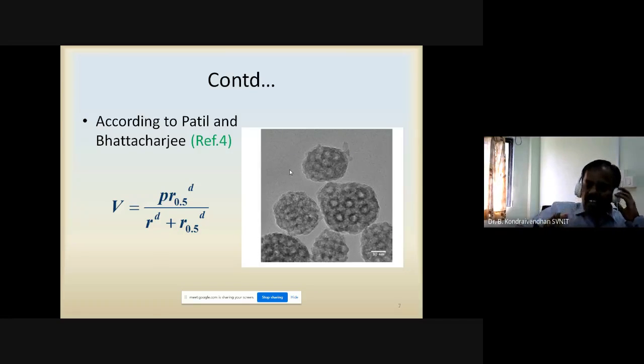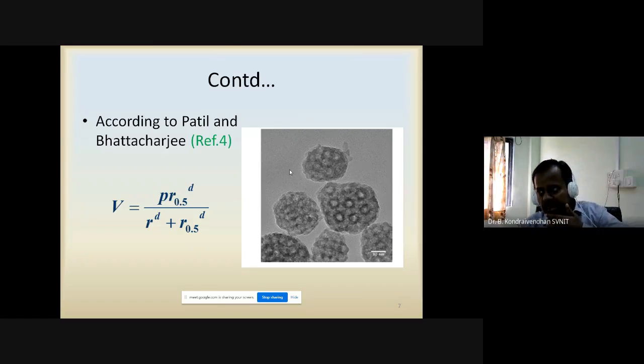There is a lot of research that has been done on this. Actually, we are the pioneers in this research also. Professor Bhattacharya and Patil have done some work on this cement-based material, and they found that pore size distribution is governed by three parameters. One is the permeable porosity P, R.5 is the mean distribution radius, and D is the dispersion coefficient. So I am clearly explaining here what R.5 is: R.5 is the pore entry radius, D is the dispersion coefficient, that is the distance between the pores, and P is the permeable porosity. If you know these three parameters, and you are able to model them as functions of simple mix parameters like water-cement ratio, curing age, and mean cement particle diameter, then it is possible to determine the pore size distribution parameters. Once you determine the pore size distribution parameters, it is also possible to predict the compressive strength, and also the permeability. Everything I am going to explain one by one.